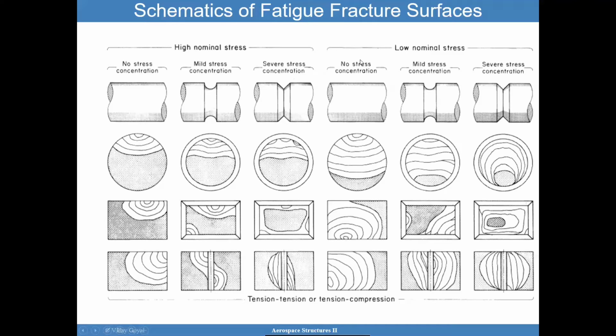For a lower nominal stress situation, notice how you're going to have beach marks that travel more with a final ductile failure. That makes sense because you're giving an opportunity for the fatigue crack growth to occur, right? Here, if I have a higher nominal stress, then it will grow some, but then break suddenly. So that makes sense. If I go with a mild stress concentration, again, this beach mark starts getting pulled downwards